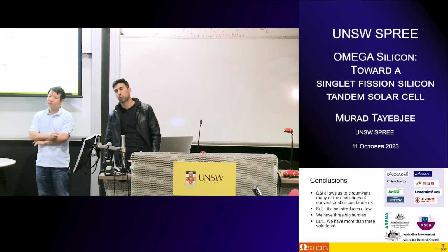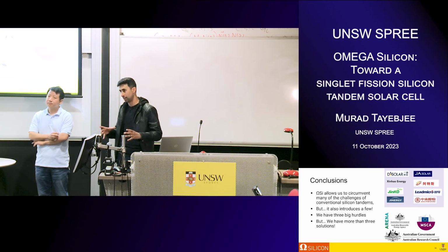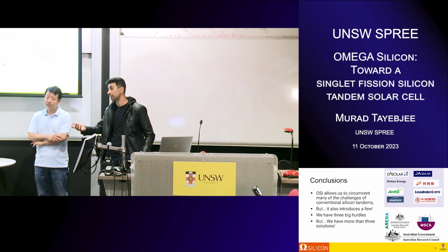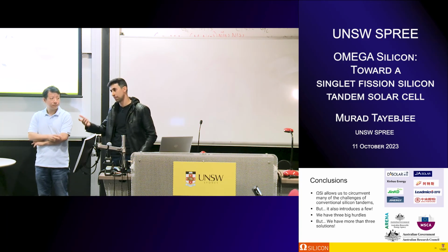In parallel. We'll first get that so we don't have to put contacts on every device. But once we have that PL optimization, where we say that's a result, then we move to MPC, which is magnetic field dependent photocurrent. And if we see that same trend in the photocurrent, then we know that the triplets are being injected into silicon and also collected as charges.